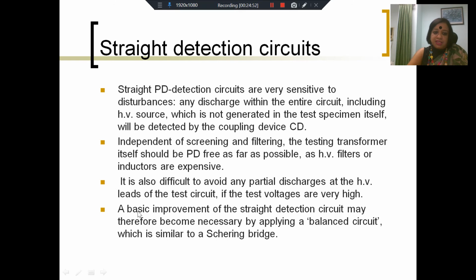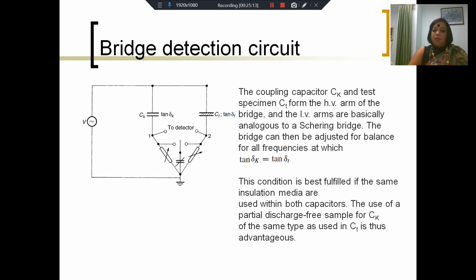And therefore what we do is we have a basic improvement of the straight detection circuit, and sometimes instead of using a straight detection circuit, we use what is called a balance circuit, a bridge circuit. This bridge circuit is very similar to a Schering bridge. We've not yet discussed the Schering bridge, but it is a bridge circuit where we balance it out and only measure the imbalances. This is the basic principle of the bridge detection circuit used in PD measurement. You have the voltage as before, you have the coupling capacitor here, you have the test specimen here, and the rest of the circuit is now modified to form a bridge. The coupling capacitor CK and the test specimen CT form the high voltage arm of the bridge, and the low voltage arms are very similar to the Schering bridge which we will study later.